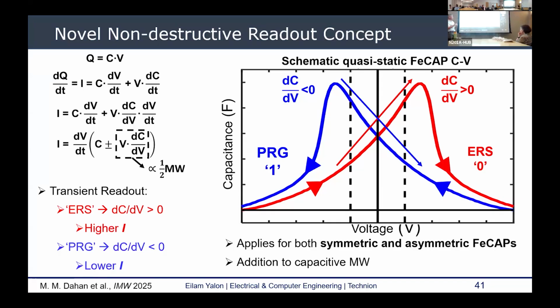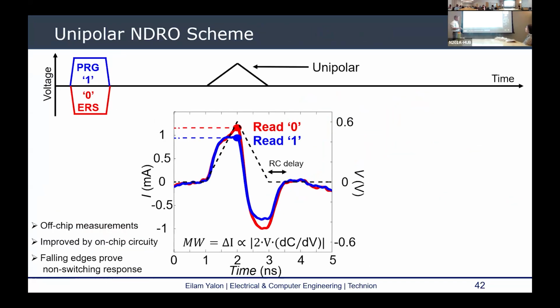And that means that we can apply a small transient, even very close to zero bias, where there is no difference in the capacitance or a very narrow difference in the capacitance. And we need to apply very short pulses to get this signal, so delta t has to be short. But if we get that, then we'll see a difference: in the erase state, we'll have higher current because dC/dV is positive, and the program state will have lower current because it's negative. And we're actually able to capture this phenomenon. So this, the dashed line, is the voltage waveform, 0.6 volts. It's about a nanosecond time scale.